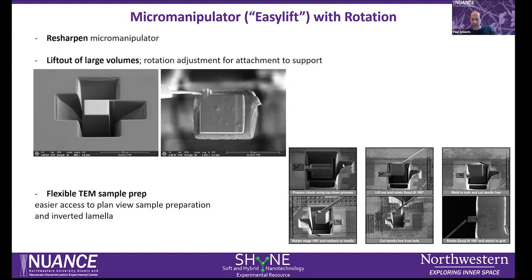So there's a series of steps you would need to take. For example, if you rotate the micromanipulator 180 degrees, that results in a rotation of your sample of 90 degrees. So you lift it out, rotate it, attach it, cut it free, then rotate the sample stage 180 degrees, lift it out again, rotate it back again, and then mount it on a FIB grid.